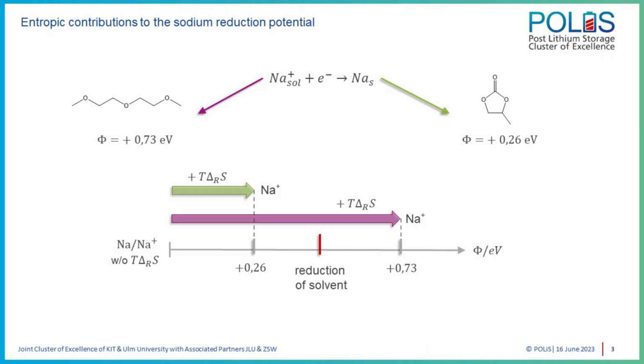By the value of the reaction entropy, we are able to determine the entropy contribution to the free enthalpy of the sodium reduction, which amounts to minus 70 kilojoules per mole in diglyme and minus 25 kilojoules per mole in propylene carbonate. And since the free enthalpy correlates directly with the galvanic potential, the entropy change also affects the reduction potential of the sodium ions. And the values of the reaction entropy we obtained from our measurements correspond to a positive shift in the redox potential of 0.73 volt for the sodium ions in diglyme and about 0.26 volt in propylene carbonate. So in both systems, the entropic contribution leads to a destabilization of the sodium ions. However, the destabilization is significantly higher in diglyme solutions.